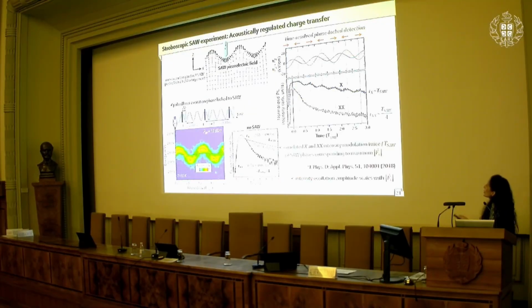Now, in the stroboscopic experiments, which are performed with time-resolved pulsed detection in this case, we also see that when we apply the acoustic waves, during the decay of these exciton and biexciton complexes, we do observe some small changes in the intensity of these peaks, like you can see here. So if we follow the slow PL decay, such as that of the exciton in the absence of the acoustic wave, we see that these oscillations appear twice per acoustic cycle and that they take place at well-defined phases of the acoustic wave, which basically correspond to the maximum value of the longitudinal piezoelectric field component of the acoustic wave, marked by these red arrows here.